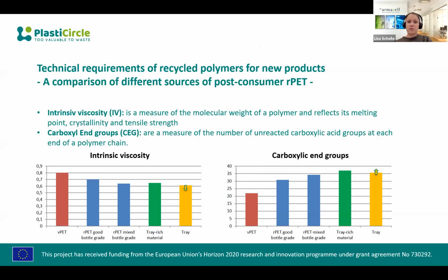So we first had a look at analyzing different PET materials on lab scale. We started with testing the intrinsic viscosity, the CEG, and the molecular weight distribution. And in each test, we compared the tray material provided by the project with different materials from different sources, like virgin PET, recycled PET from bottles with different quality, and tray-rich material, which is a mix of PET from bottles and PET from trays. In the graph, you can see the results for IV and CEG.